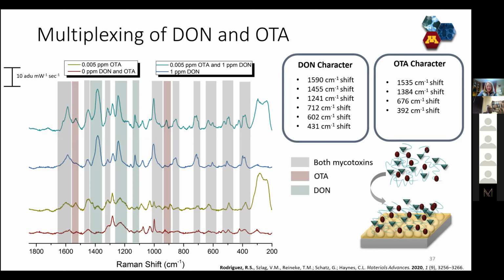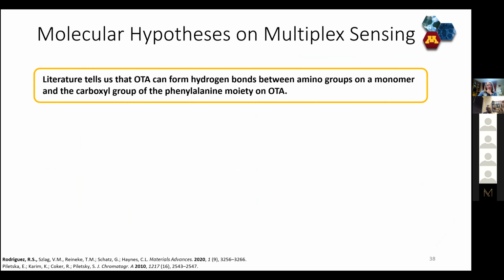The green bars that I have there are the peaks that show up that are very clearly due to the DON. The red ones, there's only two of them, but they are the ones that show up only with ochratoxin. And then all those gray bars are features that change in both cases. That's either because they have shared vibrational modes or because it's actually a change in the polymer when it binds to one of the two toxins. But either way, lots of very specific bands that we can look at to distinguish that both mycotoxins are there.